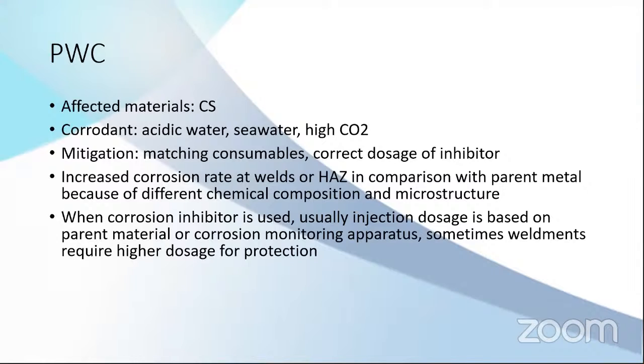And the problem is that the weldment is not fully protected by the corrosion inhibitor, so it can get preferential weld corrosion as well. So when you use corrosion inhibitor, normally the best practice is to increase the dosage a little bit to make sure that the weldments are protected.